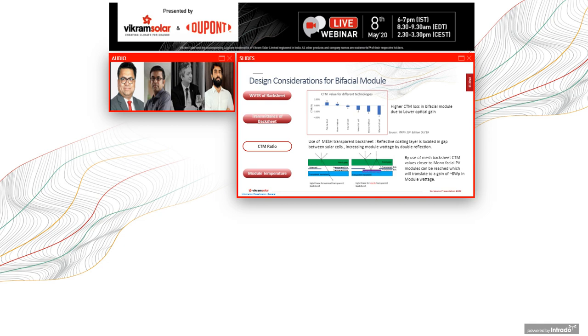Now, there are transparent backsheets to mitigate this issue. There are transparent backsheets which use a mesh or a reflective mesh layer at the gap between adjacent cells, where it creates an additional reflecting surface over which the light can get reflected and be incident on the cell once again, so that you can recover some of that light that was escaping. And therefore, using a mesh backsheet will help you to gain back some of those CTM losses that you are actually losing.